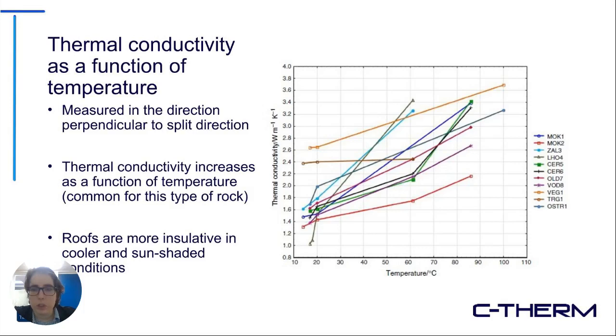And on this plot, you can see the thermal conductivity behavior in the direction that is identified on the previous slide as perpendicular. So it's basically in the through-plane direction. And for these slate materials, as with most metamorphic and sedimentary rocks, you see that the thermal conductivity actually increases as a function of temperature. This is not uncommon for these kinds of materials. What this does indicate, however, is that the roof is going to be more insulative in cooler and sun-shaded conditions than it would be in the heat of summer, which suggests that it will be more effective at retaining heat in the winter than it would be in retaining air conditioning in the summertime.